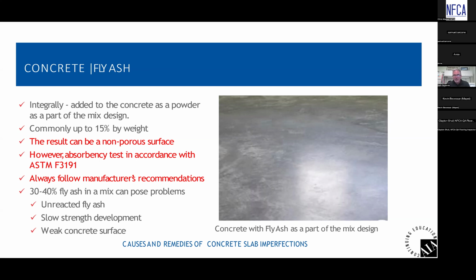So from a flooring adhesive standpoint, it may mean a different adhesive. It may mean a different notch trowel for the adhesive you were going to use, maybe a smaller notch. It may mean a longer open time for that adhesive. Okay, but when you're testing for absorbency and seeing that it's not absorbent, then check with your adhesive manufacturers to see what their recommendations are. Some of them, with the waterborne adhesives, go with a smaller notch trowel and longer open time. Some may want a blotter layer of a porous cementitious material. Check with your adhesive and flooring manufacturers.